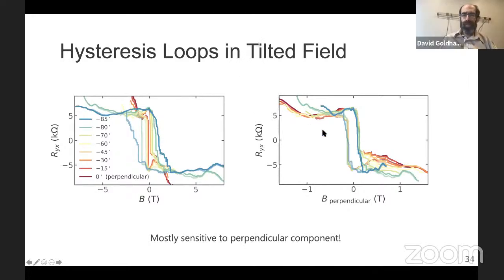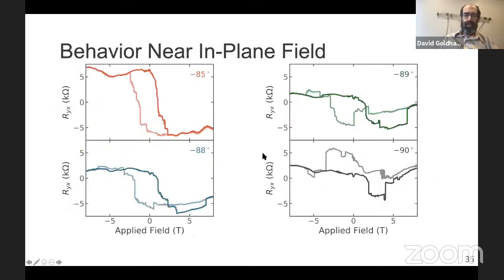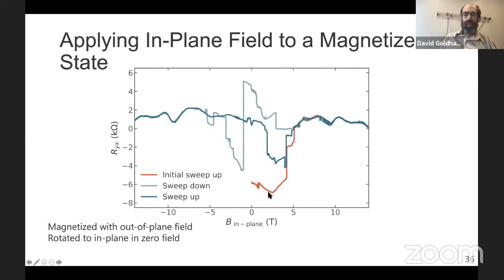So yeah, let me just say it's less understood what happens when we put on an even more in-plane field going all the way down to the plane. You can see these hysteresis loops get more complicated. And then we've gone all the way out to 14 Tesla, the maximum field that we can apply in my group. So here we polarized the system out of plane, then we rotated so that the field was in plane and started sweeping the field.